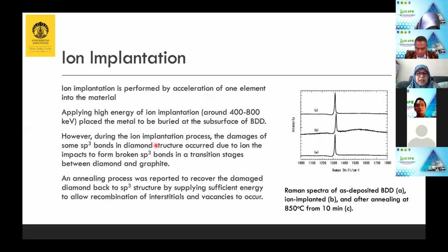But during the implantation process, actually some sp3 bonds will be damaged. For example here, this is the Raman spectroscopy of boron doped diamond before implantation. This is after implantation. We can see a peak here showing sp2. Why sp2 here? Because this process makes some sp3 broken to be sp2. And then what can we do to recover this? We can give high energy using an annealing process to give this back to sp3.